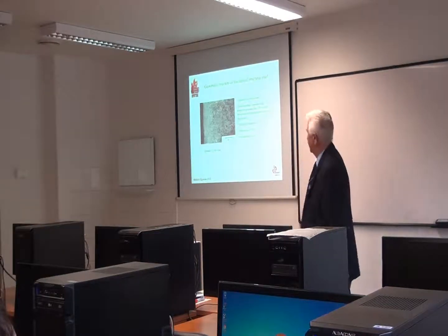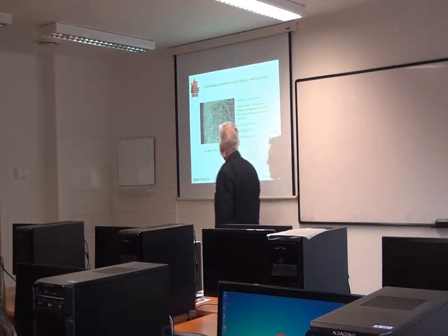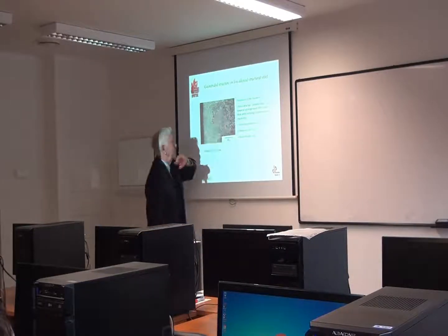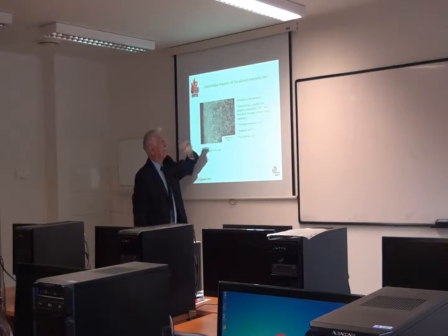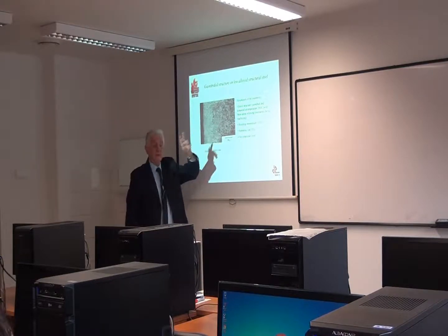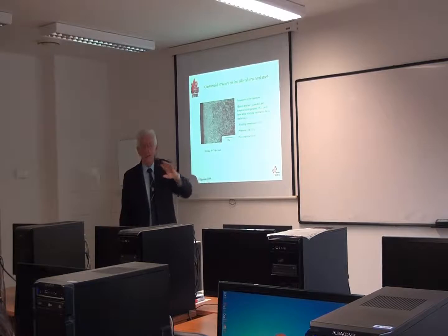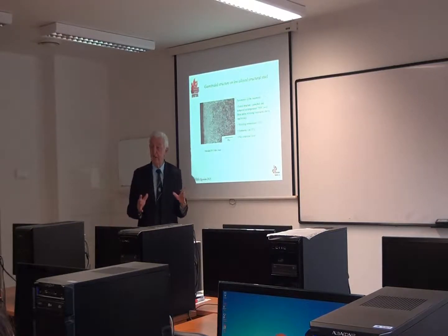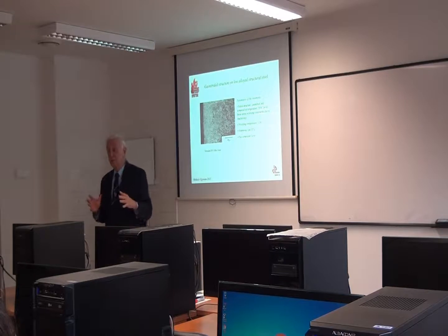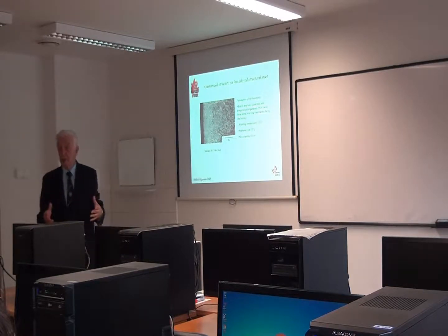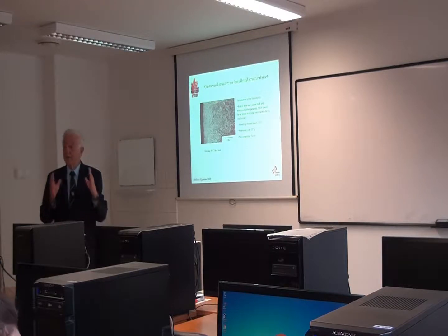You see, this is a typical structure of gaseous nitrided sample. So this is very fine. A kind of, you see, this is the lower layer still. The basic structure is a kind of tempered martensite, because for the stability, when we don't want to have any deformations afterwards during the machining and during the final finishing, we have to have a stable structure, and the only stable structure is the tempered martensite.